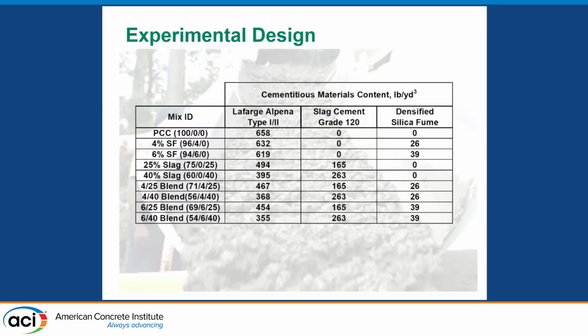One that was popular was 658 pounds of Portland cement. So what we did is we looked at what would be the impact of changing, by looking at a binary versus a binary with silica fume, a binary with slag cement only, and then the combination, making it a ternary, which is using also the blend with 25% slag cement with 6% silica fume, 25% slag cement with 4% silica fume, and then looking at these types of blends.